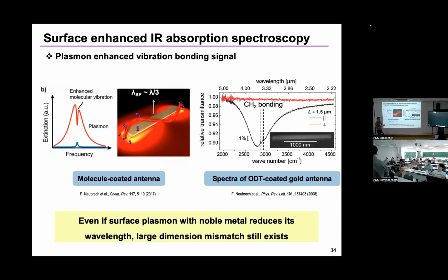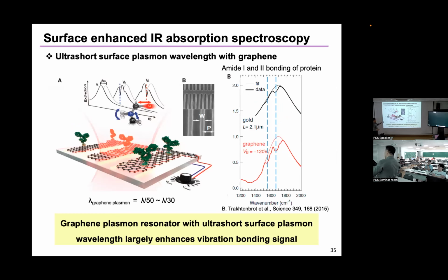So molecular vibration and the field confinement are highly overlapped, and we directly measure the molecular vibration frequencies using the transmission or reflection spectrum. 2D materials can also be measured, right? Graphene plasmons can measure the mid-IR, very long wavelength regions, and the molecular vibration spectrum can be observed using the plasmonic field confinement property.